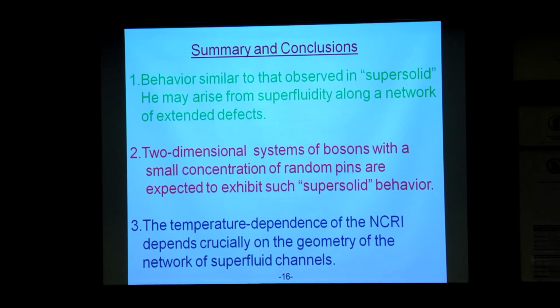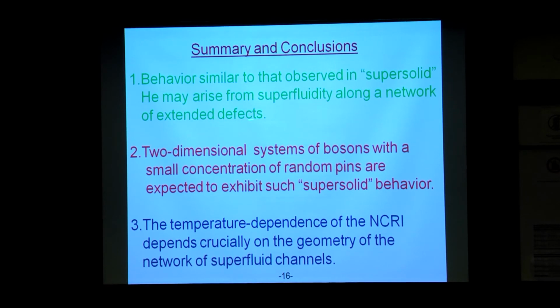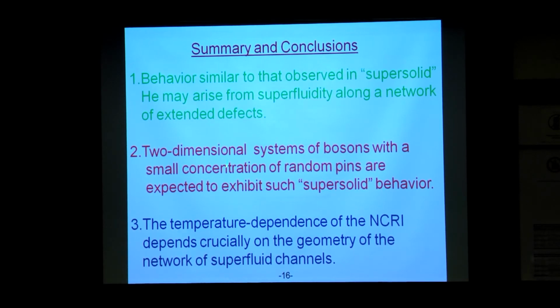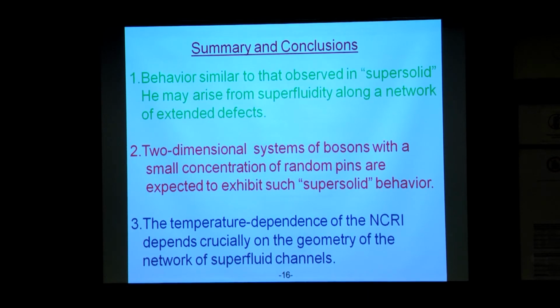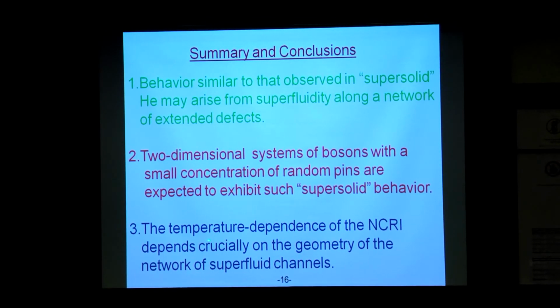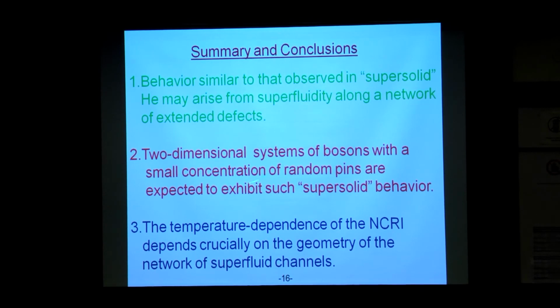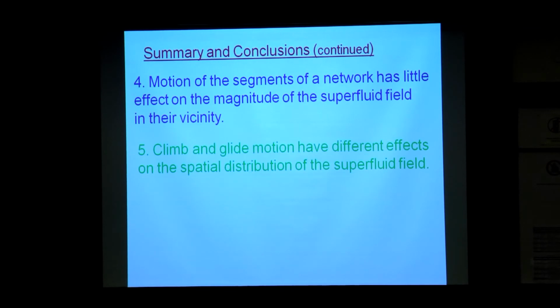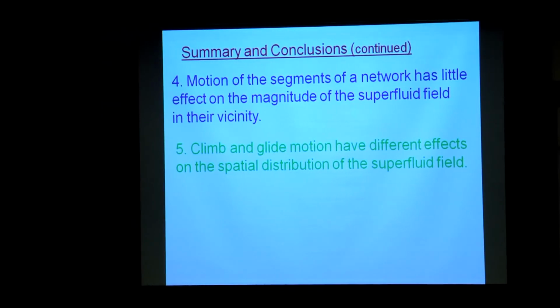So these are the conclusions. A network of extended defects can lead to non-classical rotational inertia similar to that seen in experiments. For a two-dimensional system of bosons, which corresponds to this vortex system, we can show explicitly that this is what is going to happen. Then motion of the segments has little effect on the magnitude. It has some effect on the actual distribution of the superfluid order parameter surrounding a dislocation line. So this is where, pretty much on time, thanks a lot.